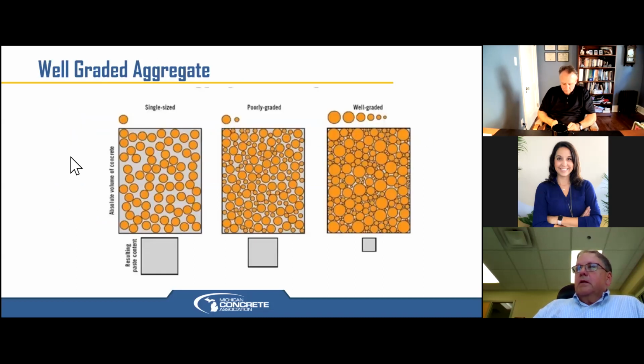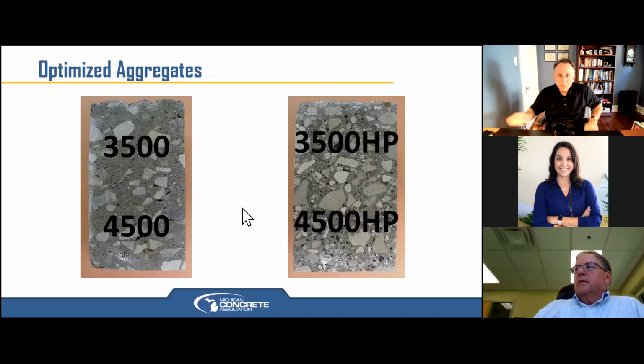And by the way, aggregates are much stronger than our cement paste, right? That's a given. So with a single-size material, you need a lot of paste to fill in all the gaps. Poorly graded, you still need a fair amount of grout. But when we get to well-graded, we just don't need as much glue. And we eliminate glue, we eliminate CO2, we make ourselves more environmentally friendly. And we have a mix that works much better. Here's a couple pictures. The one on the left was the standard gap graded mixes with a lot of sand and grout versus the well-graded mixes where we've added these smaller aggregate chips.